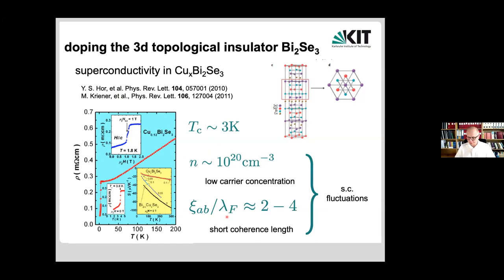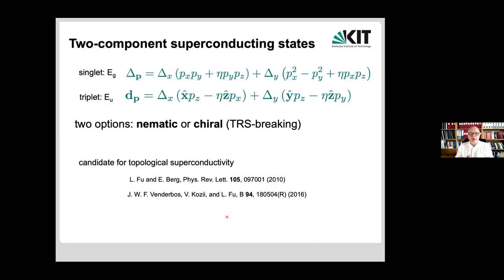So there is some hope that superconducting fluctuations in this system could be more important and relevant than in many other systems. In order for this to work, you do need a two-component order parameter, and the underlying point group, which is trigonal, has two options. One is a singlet or a triplet, EG or EU order, a two-component order parameter, where the two components are just given here, and our basis functions are a little bit lengthier because of the point group of the system. And you find that regardless of whether this is odd or even pairing, you can make essentially a nematic or a chiral, time reversal symmetry breaking superposition.